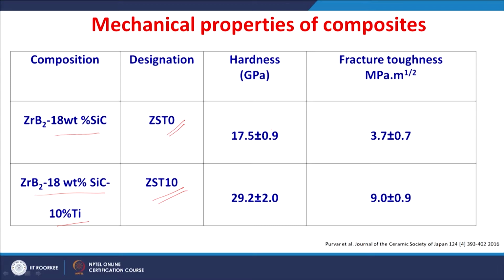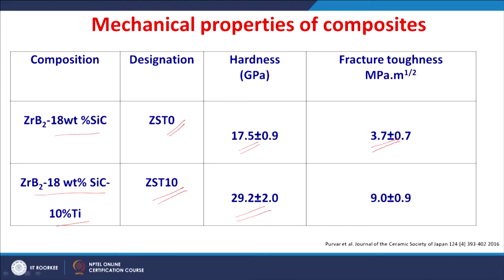The hardness and the fracture toughness values were determined by Vickers indentation. You can see the hardness increased from 17.5 gigapascal to around 29.2 gigapascal by adding 10% titanium in the baseline composition of zirconium diboride silicon carbide. And fracture toughness also improved from 3.7 to 9.0 MPa root meter. So, you see there is very large improvement in the hardness and fracture toughness by adding only a smaller amount of 10% titanium in the composite.